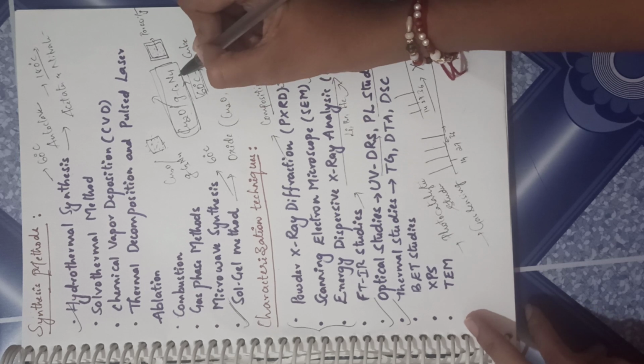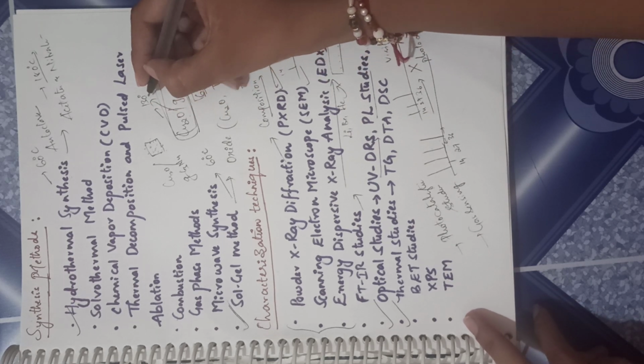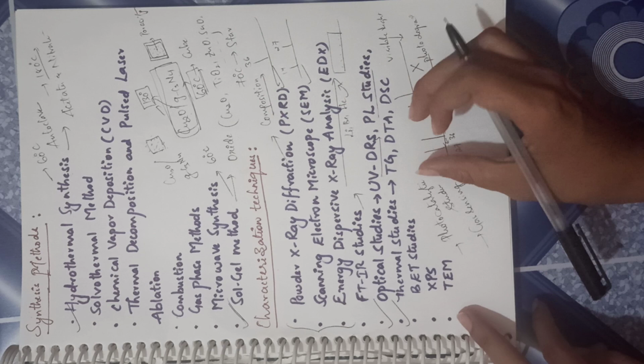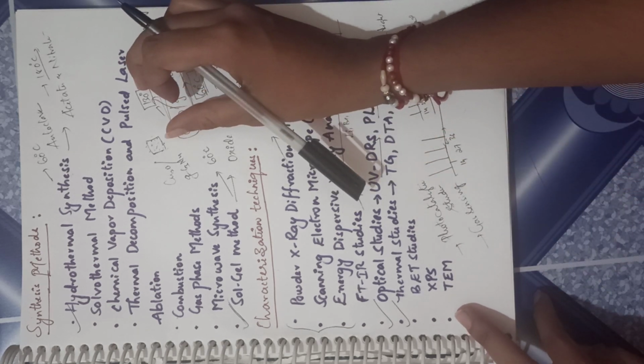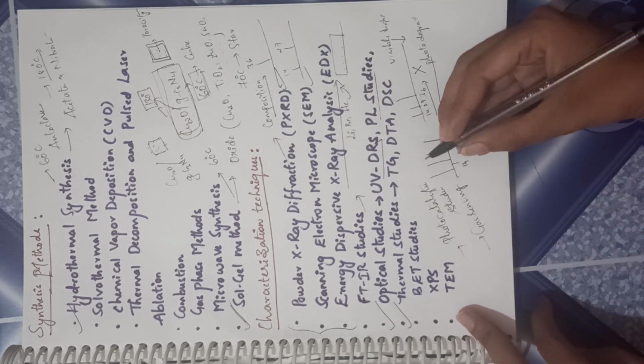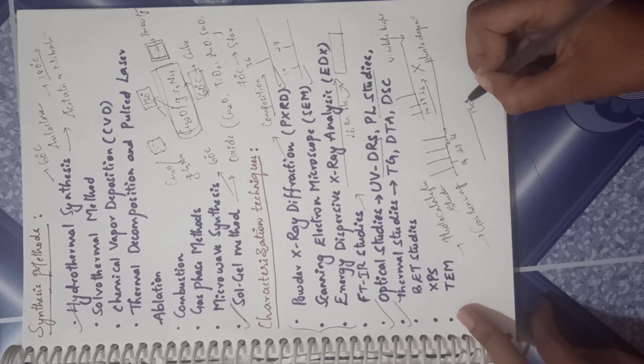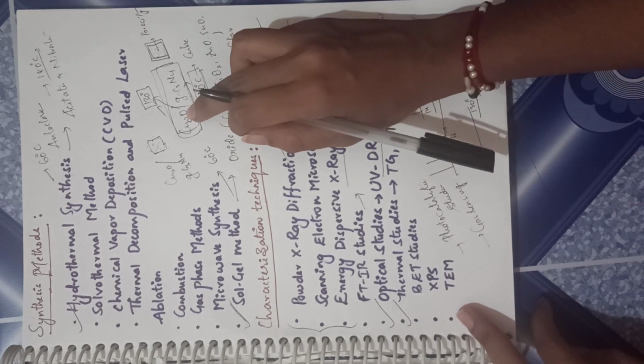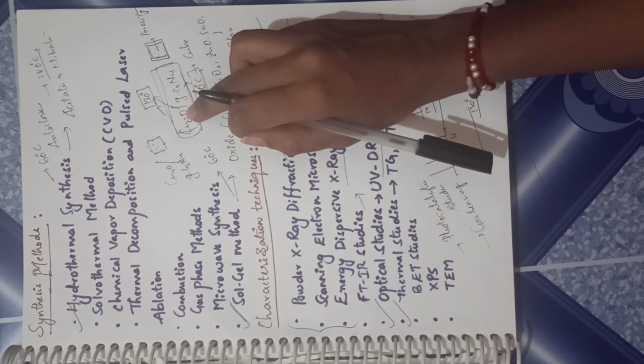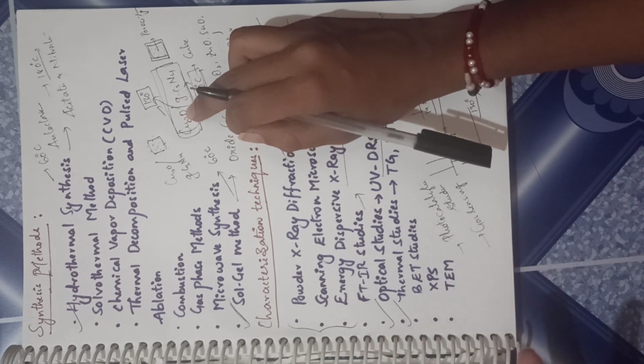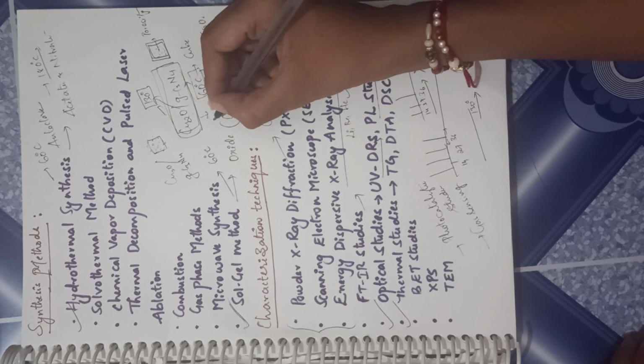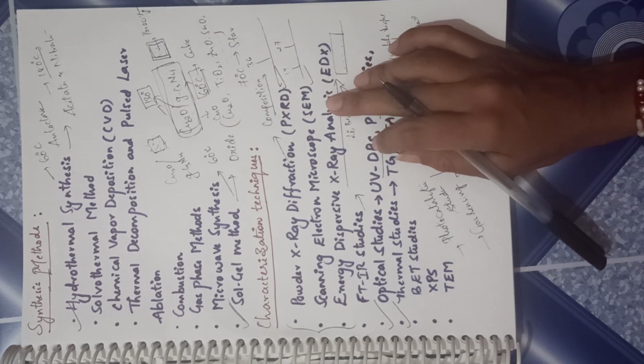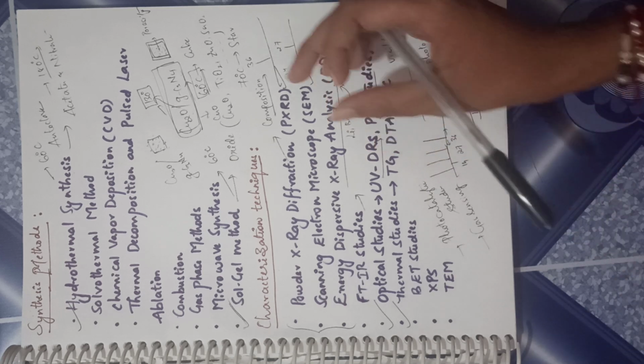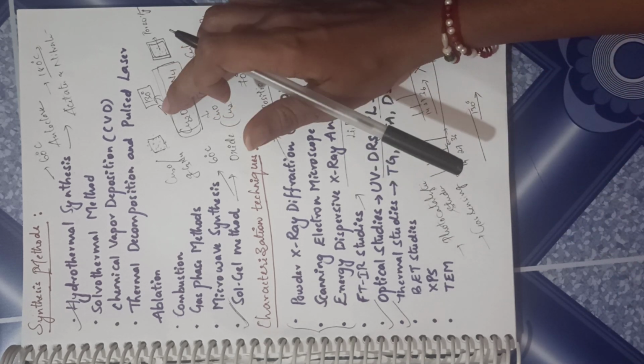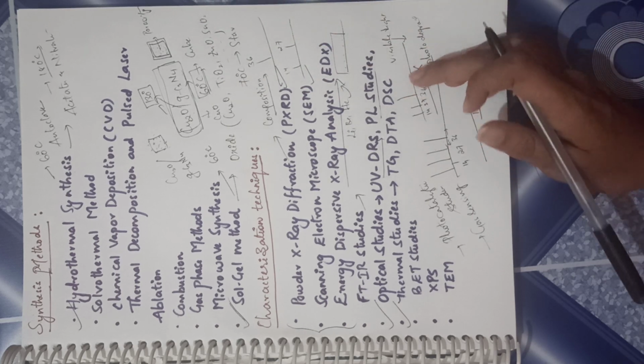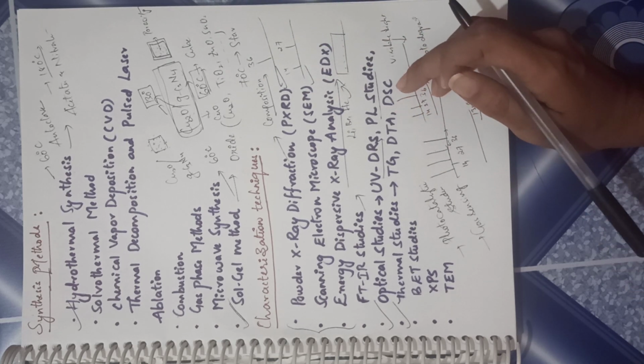Let's say this material is stable only till 130. How do I know it is stable only till 130? Using TGA. Once I know it is only till 130, whenever I do gas sensing experiments, I'll go only till 130. Beyond that, I won't go, because there is a possibility, it's not a possibility, there actually what happens is Cu2O gets converted to copper oxide. That is, oxidation takes place. So the whole material properties will be changed if it is +1 to +2. Okay, and you do also DSC.